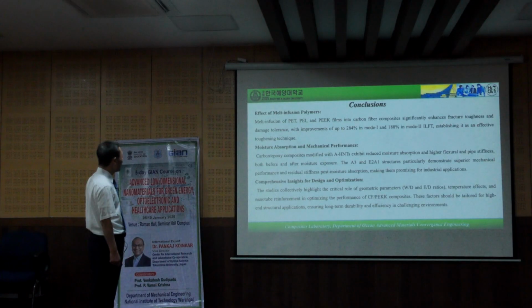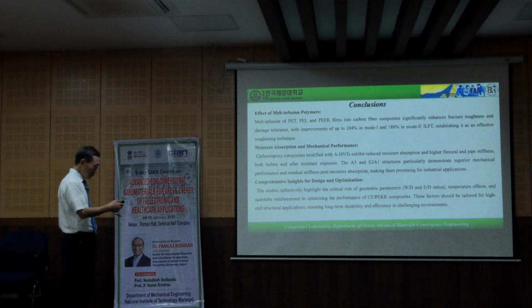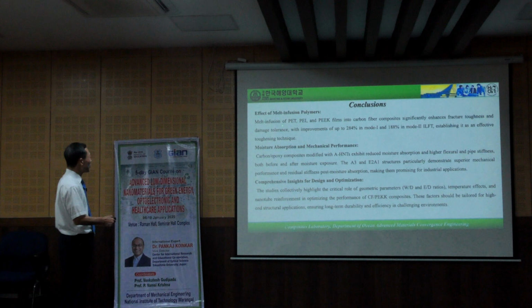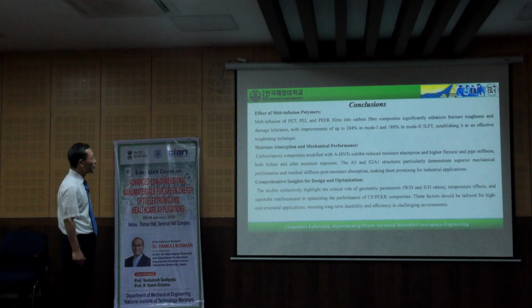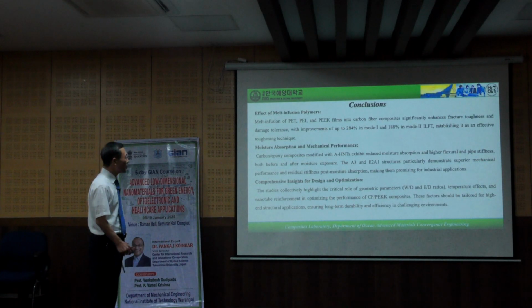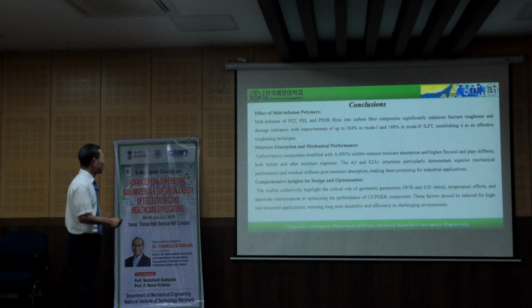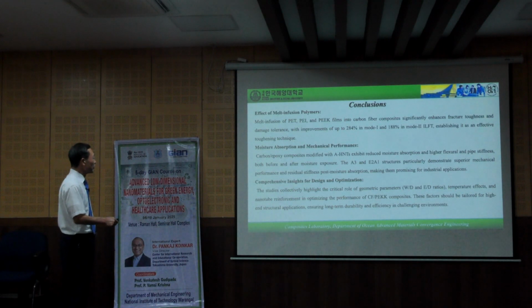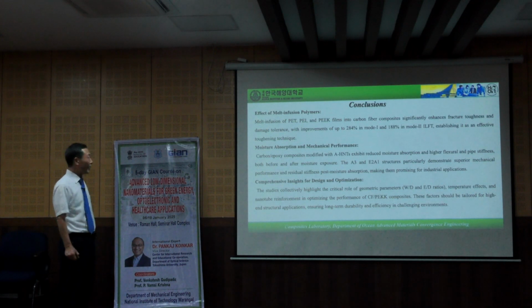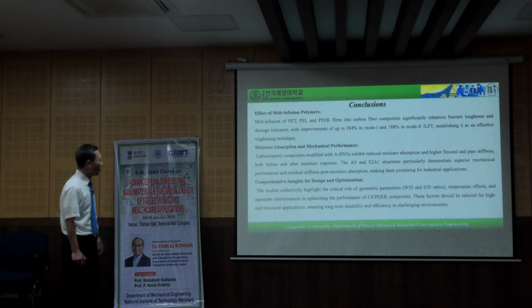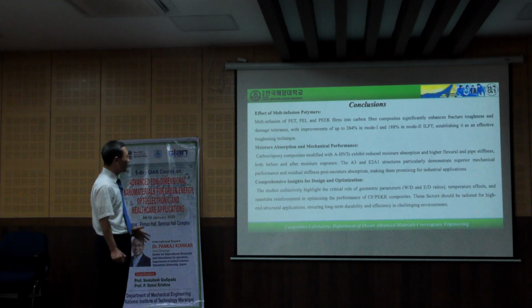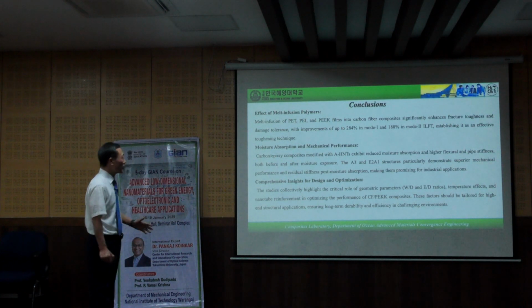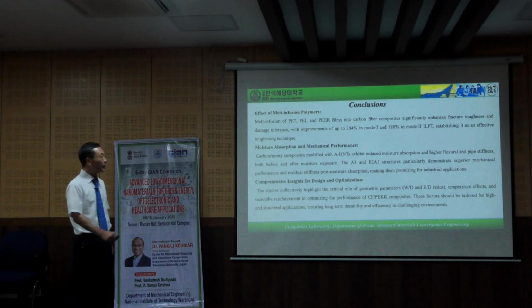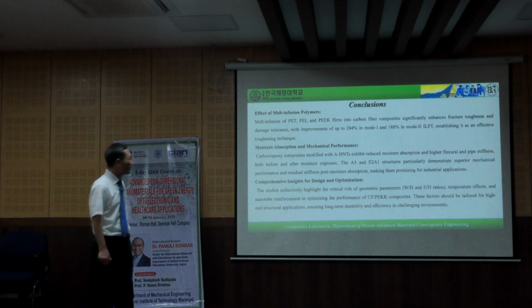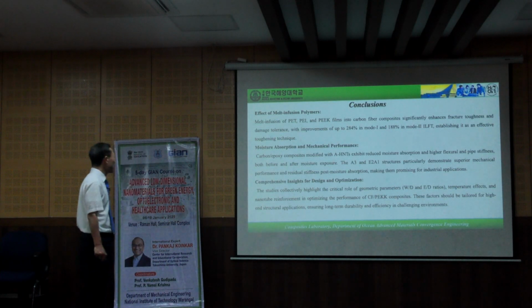Regarding the effect of melt infusion polymers, melt infusion of PET, PEI, and PEEK films into carbon fiber composites significantly enhances the fracture toughness and the damage tolerance with improvement of up to 284% in mode 1 and 188% in mode 2. Interfacial interlaminar fracture toughness, establishing it as an effective toughening technique.